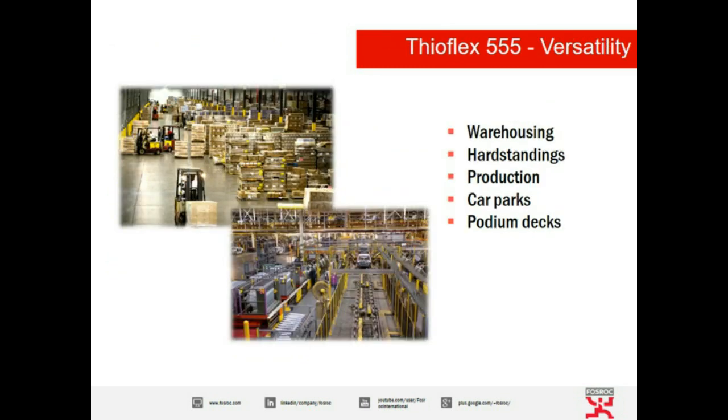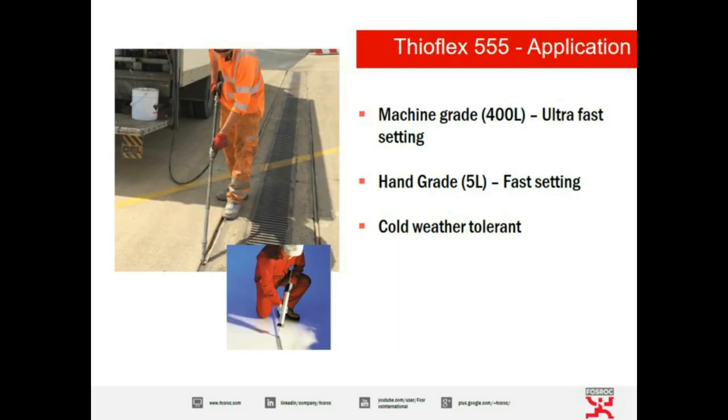In terms of the versatility of the product, before I mention the areas where it can be used, I think one of the important points is that rapid return. To give you an idea of the return to service of 555, just jumping back one slide here to our chap applying the material: 20 degrees, half an hour, and then right the way down to 5 degrees, 90 minutes maximum.